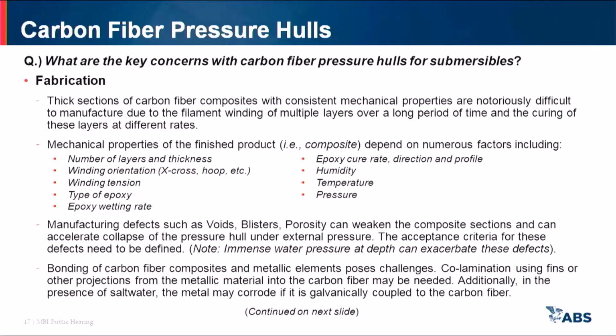So one of the processes used for fabricating carbon fiber composite pressure hulls is the filament winding process, in which the pressure hull is created by impregnating or coating the carbon fiber strands with epoxy and then winding them in a precise geometric fashion over a mandrel. So a mandrel is basically a tool in the shape of a cylinder. So on the cylinder, you wind the carbon fibers which are impregnated with epoxy, and then you cure that cylinder in an oven at 1 atmosphere or in an autoclave under pressure.